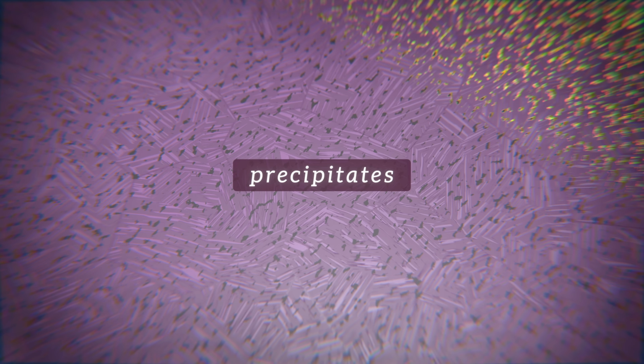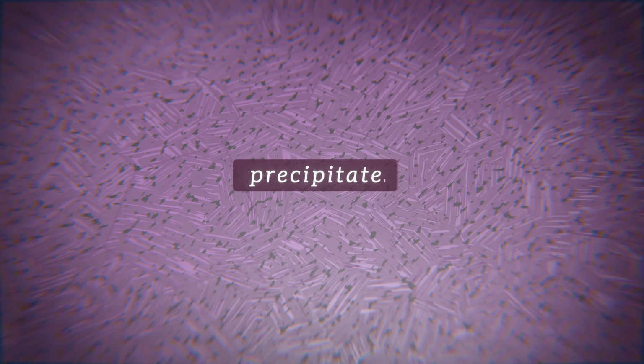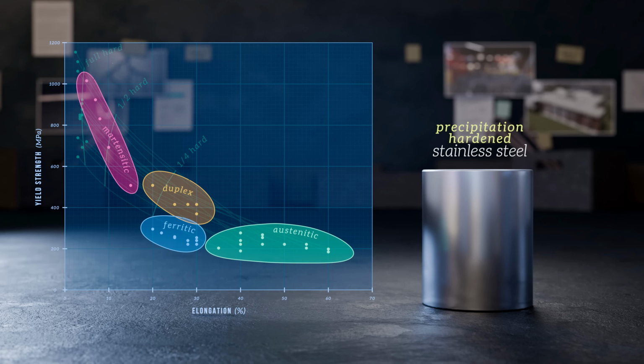These precipitates impede the motion of dislocations and give PH steels exceptionally high strength, often while still retaining more ductility than conventional martensitic grades. The most common of these is 17-4 PH. It includes 3 to 5% copper, allowing it to form a fine dispersion of copper-rich strengthening precipitates during aging.